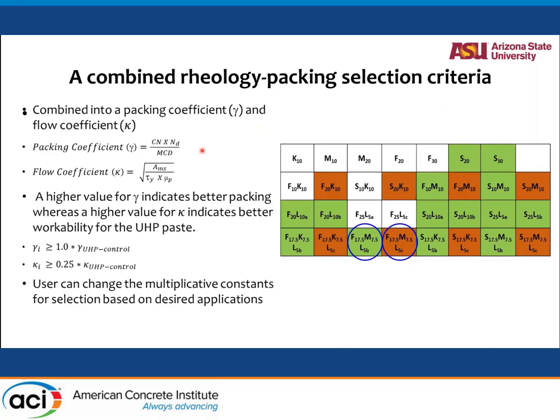We came up with a simple packing coefficient based on the values of coordination number, number density, and centroidal distance, one which will go up and come down, just to get you a value that can be reasonable in terms of a number. And then we developed a flow coefficient, which is the square root of the mini slump area multiplied by yield stress and plastic viscosity. Higher value for gamma indicates better packing. Higher value for kappa indicates better workability. For these parameters, we took multipliers as 1 and 0.25. The packing coefficient has to be greater, which means better than the control, and the flow coefficient has to be greater than at least 25% of the UHP control.